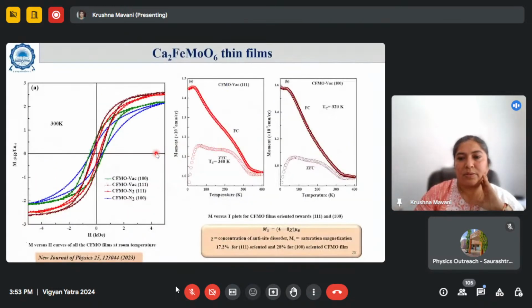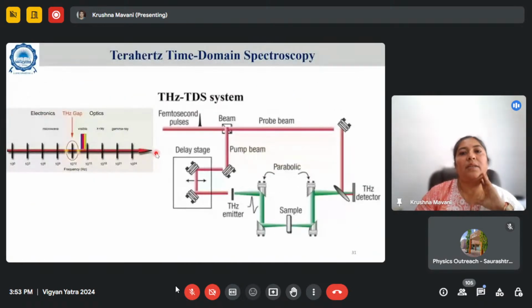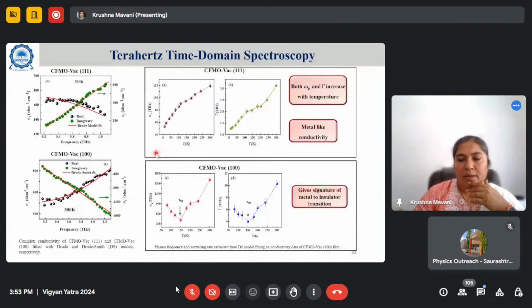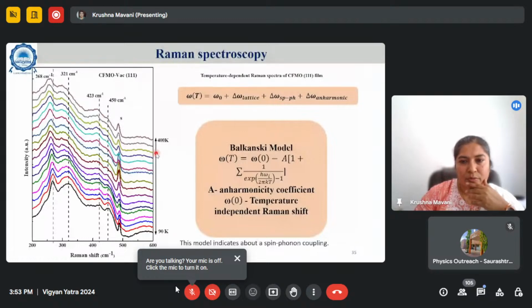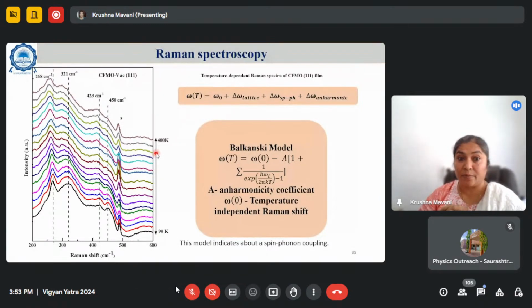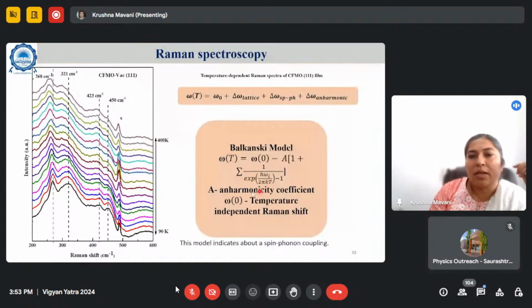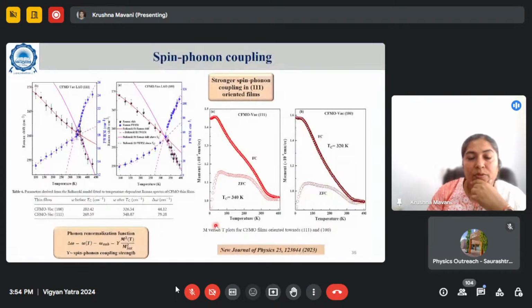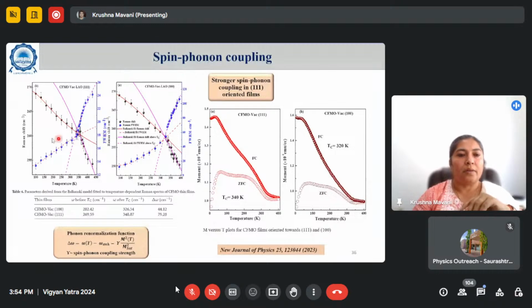That also we have proved efficiently using a variety of experiments, including terahertz time domain spectroscopy and Raman spectroscopy. In Raman spectroscopy, we have done temperature dependent Raman spectroscopy of selected thin films having very good cation ordering, and we found that this variation in Raman shift can be fitted to the Balkanski model, and that the anharmonicity coefficient in the Balkanski model can help to understand whether there is any coupling between spin and phonon. So spin phonon coupling can be seen in our results very clearly, because you can see drastic deviations from the trends near transition temperature.